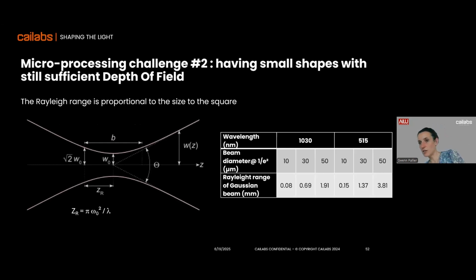Another challenge, which is somehow linked also to the laser, is the size of the part that you want to dimension. So you all know that the Rayleigh range is actually proportional to the square of the size of the beam. So when it goes to a very small beam, it's a little bit catastrophic. If you go to a beam which is 10 micron, in the end the Rayleigh range is 80 microns, so extremely small, not industrial at all, and that makes it super challenging somehow.